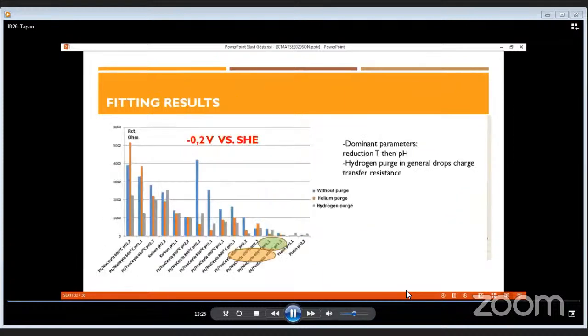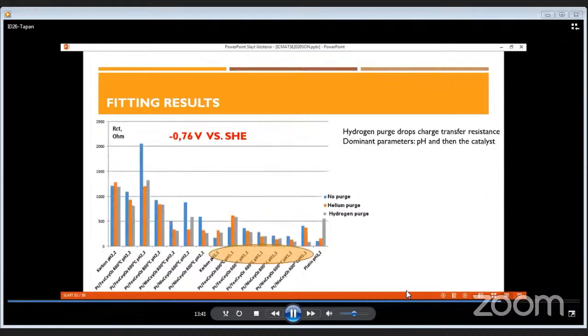If we look at the effect of synthesis and experimental parameters on the charge transfer resistance, we see that reduction temperature is the dominant factor on the charge transfer kinetics, and then pH becomes the second dominant parameter. At more negative potentials, it is clearly seen that lower charge transfer resistance is mainly affected by lower pH and then the catalyst type.